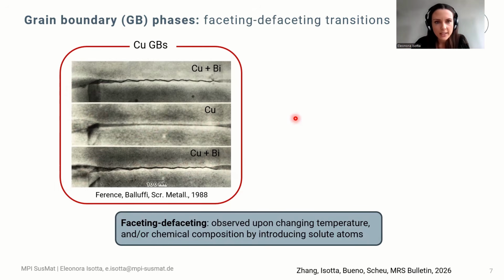The very interesting thing that actually proves the transition nature of these boundaries is that when the bismuth was reintroduced with an additional subsequent thermal treatment, the boundary took on again the faceted morphology.